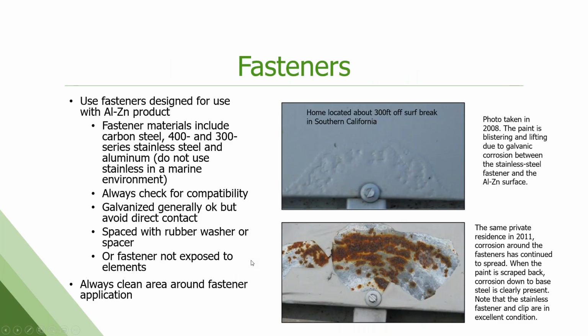So you've got to use fasteners designed for an aluminum zinc product. Again, there are guidelines on this everywhere. There's a whole technical bulletin for Galvalume just on fasteners. Carbon steel, 400 and 300 series stainless steel, and aluminum are really good. Unless you're in a marine or corrosive environment, then you do not want to use stainless. So you want to check for compatibility. Galvanized is generally okay, but avoid direct contact. You want to use rubber washers and spacers on your fasteners, and then always clean around afterwards.